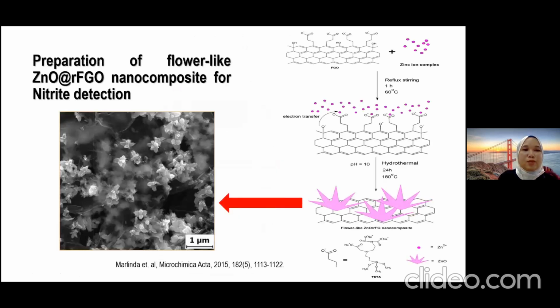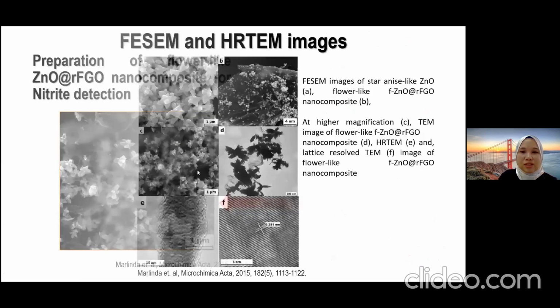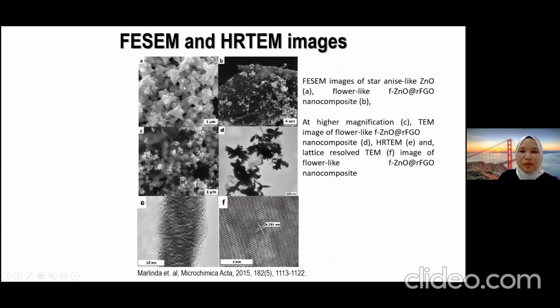Okay, this is the third one, the preparation of flower-like zinc oxide reduced functionalized graphene oxide nanocomposite for detection of nitrite. So we are using the hydrothermal method to produce flower-like zinc oxide reduced functionalized graphene nanocomposite. So there is a clear picture here where the FESEM image showing the flower shape of the zinc oxide that anchors on both sides of the reduced functionalized graphene sheets. Okay, here is the front and there is another at the back.